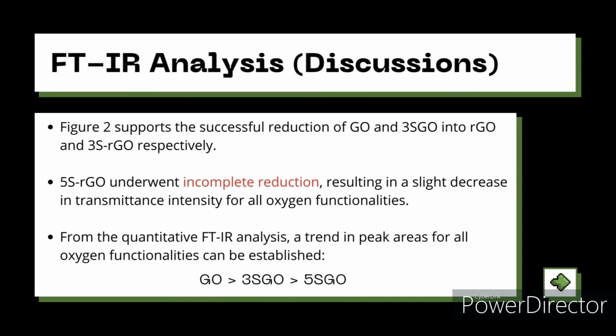The FTIR spectra showed a significant reduction in transmittance intensity between GO and RGO samples, which confirmed the successful reduction of GO and 3SGO. However, again for 5S-RGO, it showed an incomplete reduction with major transmittance intensity only partially reduced. When comparing Figure 2 and Figure 3, two opposite trends can be established.